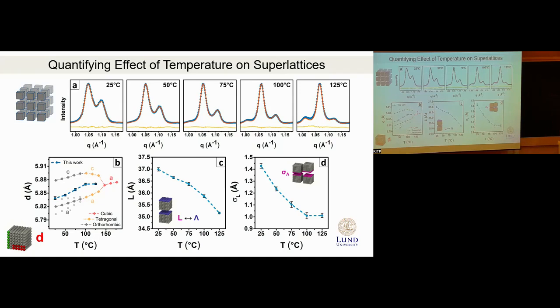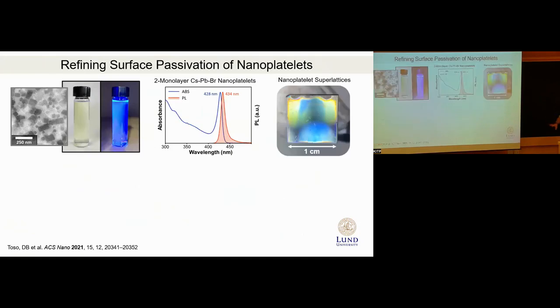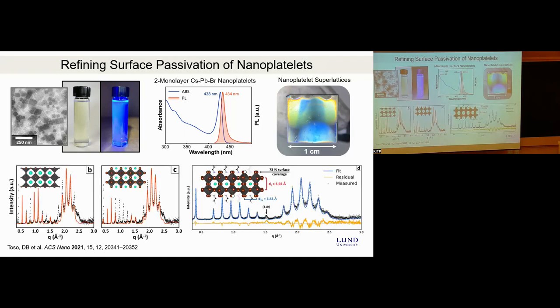Okay, so then we extended this to the nanoplatelets because you can grow these very nice 2-monolayer nanoplatelets and form, again, large films that are iridescent. We applied this method because with nanocubes you treat a nanocrystal as impersonal scattering planes. With the nanoplatelets, which are much thinner, you can assign an atomic scattering factor to each plane, and that helped us, for example, refine the surface passivation of the nanoplatelets. We found that these nanoplatelets are passivated with oleylammonium molecules, with only about 73% surface coverage, and they have a distorted crystal structure.